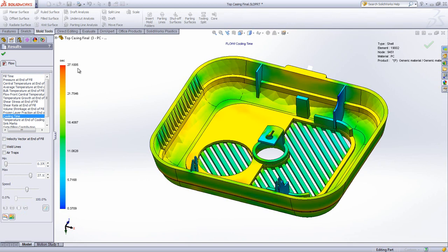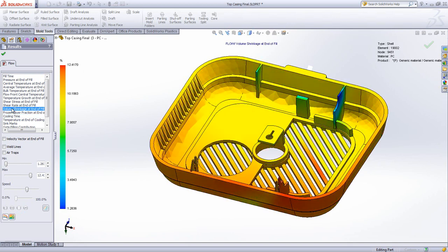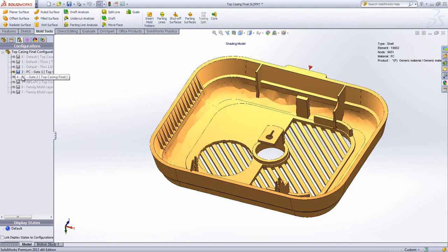It's because the wall thickness usually drives the cooling time. And the cooling time is often about 70% on average of the overall injection molding cycle time. This means that by improving the geometry of your model, you can reduce the cycle time and also lower the price per part.